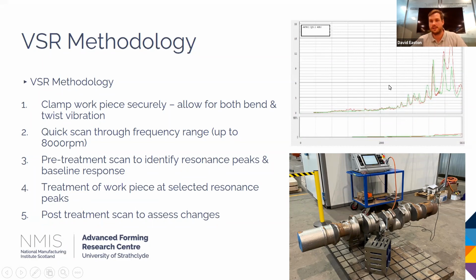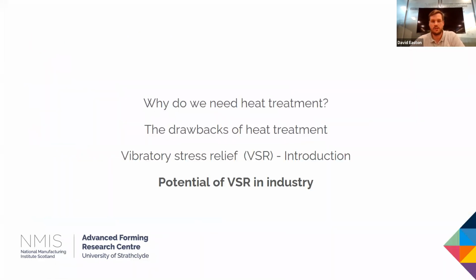So here you can see in green the scan before VSR, and then afterwards the scan post-VSR. If these two scans were the exact same, it would probably indicate that not much has happened. The stiffness of the system hasn't changed. However, in this case, we can see that some change has happened, and this is what would be qualitatively associated with a residual stress reduction. So that's a bit about VSR itself,